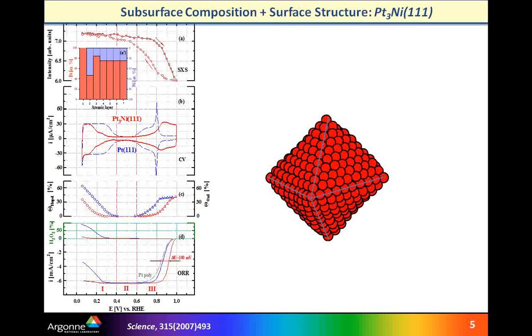Based on this, we are also using Monte Carlo simulations, and this is also, I would say, our old results, where we were suggesting that if one would be able to design or to synthesize octahedron nanostructures, then this structure may have unique catalytic activity and also stability, because at least molecular dynamic calculation shows that octahedrons are as stable as cubo-octahedron structures.